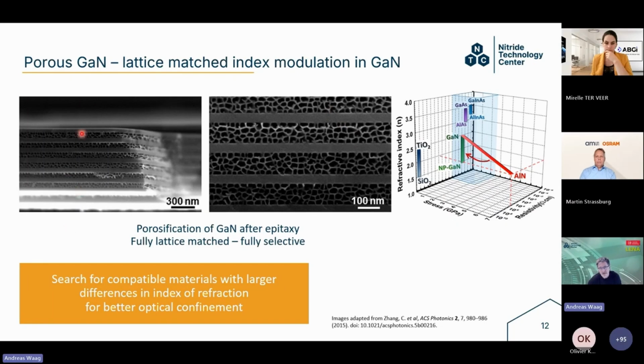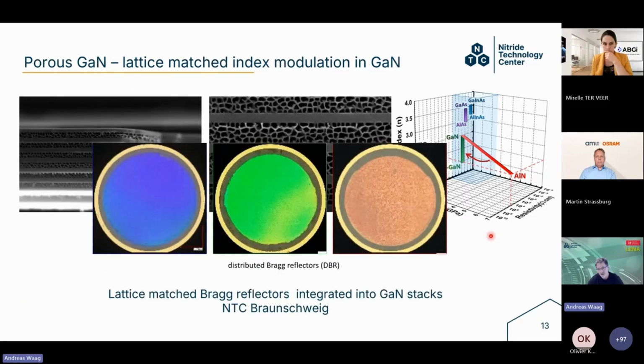So what you can do is you grow a gallium nitride stack where you can porosify parts of this gallium nitride later on. So the whole stack is fully lattice matched, but due to these pores filled with air, you have a very small index of refraction, close to 1 basically, and therefore you can introduce into a lattice-matched structure a very large index of refraction contrast. So this is one of these attempts to establish a compatible material basis for gallium nitride particularly. And this is one result from our labs, a distributed Bragg reflector, for example, for vertical cavity surface emitting lasers, fully lattice matched to the lattice constant of gallium nitride.